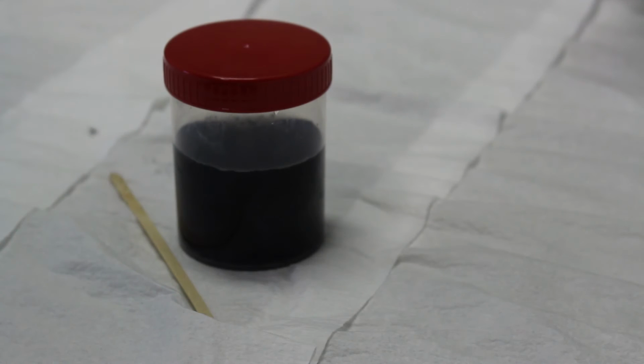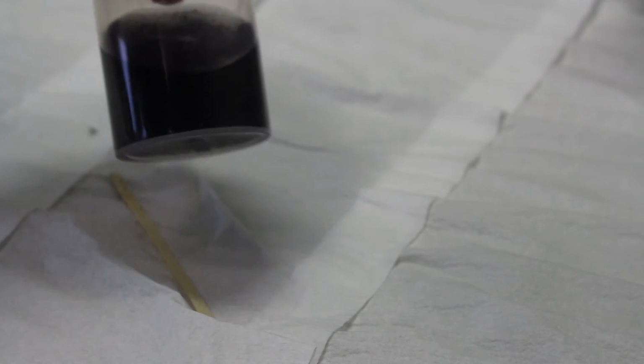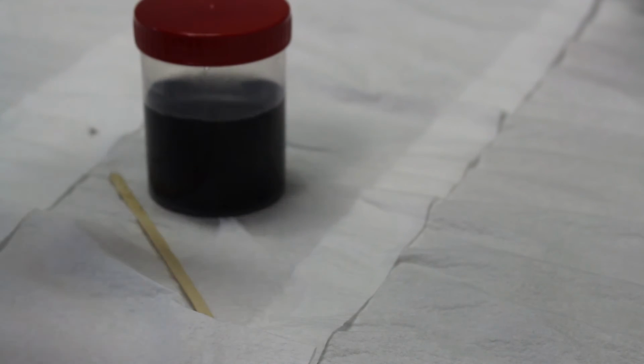So now you can see that the color changed dramatically. It's clearly darker than before. I don't know if you can notice that there are still some visible agglomerates, but the main idea is that we were able to rupture, to destroy some of the initial agglomerates, even though it was quite short. So just a couple of seconds, maybe 1 minute, of ultrasonic action has had a huge difference in the dispersion quality. So what was the point of this experiment?